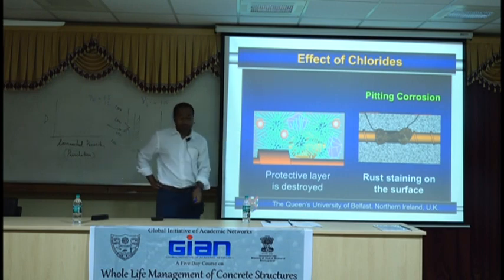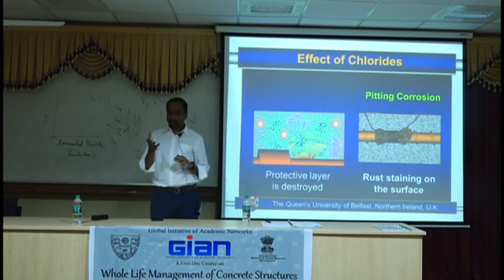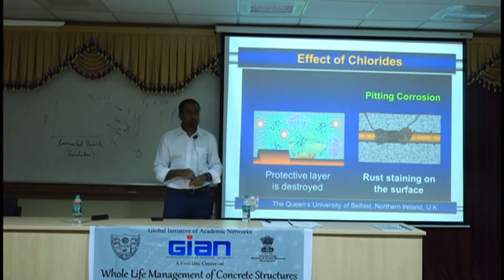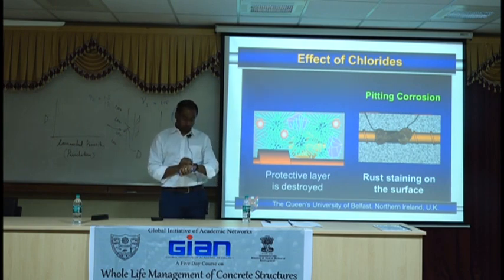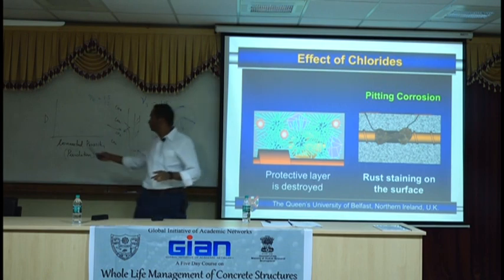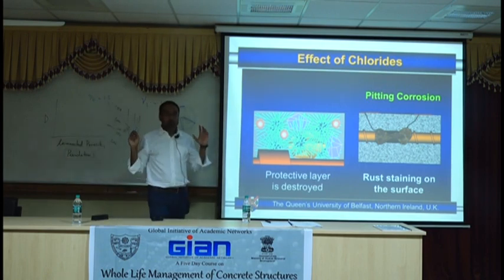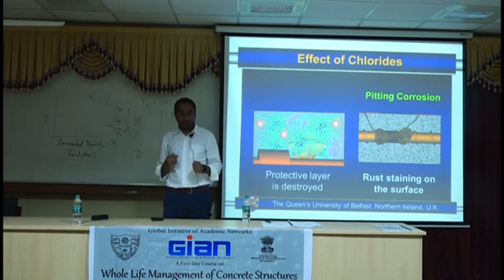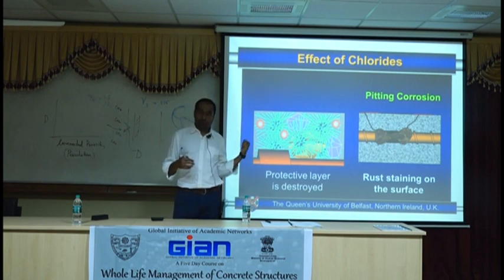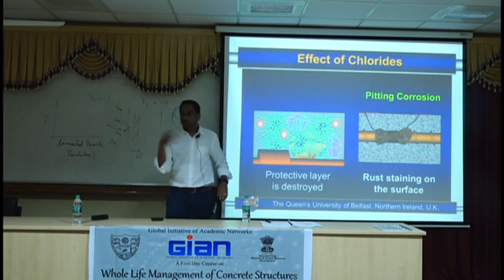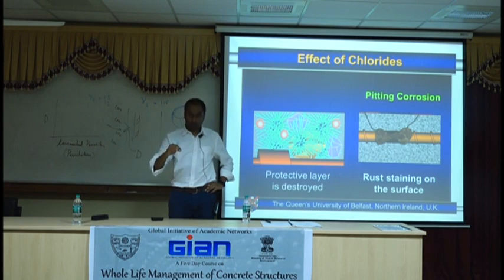So if you summarize it, what are the controlling forces that you can change to make concrete good in this environment? Primary is diffusion. Control the diffusion, control the rate of flow, you control everything thereafter. Because rate of flow is controlling the reaction anyway. If the rate of flow is low, then the reaction will be enough and sufficient to get rid of all the chlorides. So that's your primary goal, control the diffusion. What else?